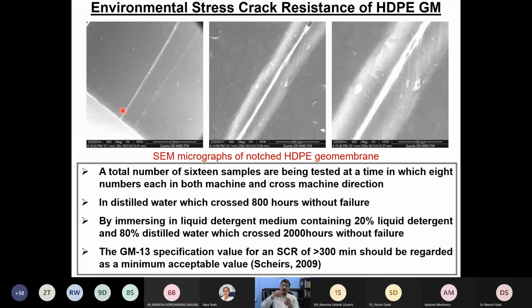As a result, at one point of time your polymer no longer fails by elongating a long way, but fails in a very brittle manner, something like a biscuit. So this also tells you whether the failure of a polymer is going to happen in a ductile way or a more brittle fashion, from the stress crack point of view. This is also going to happen in your geomembrane when it is subjected to high tensile stresses due to indentation or any other process in the landfill. You may not be able to see that the polymer has failed, but this phenomenon is going to happen. We measure the SCR value; if it is anything more than 300, people say that is really good. In our case, it was even more than 800 in distilled water. But when we dipped it into the detergent media, it reduced drastically.